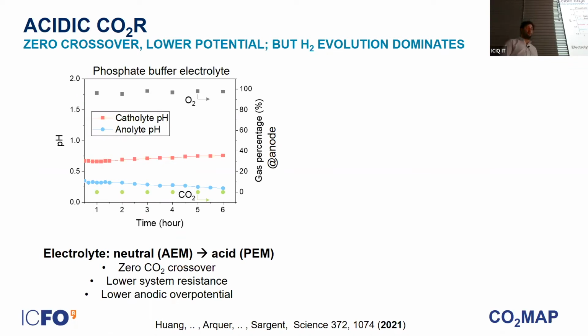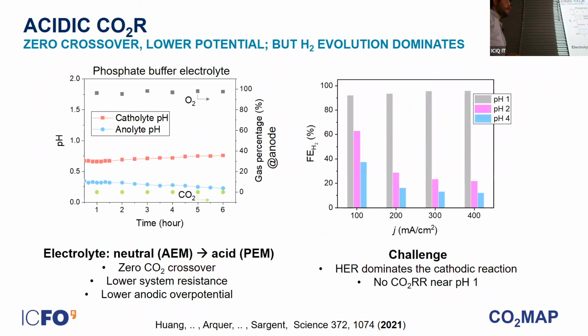We have, in principle, lower system resistance because the system is very acidic, and in principle also a lower anodic overpotential, based on the existing body of knowledge for PEM electrolyzers. But there is a problem, of course. In these acidic conditions, you have so many protons around that hydrogen evolution dominates the cathodic reaction. So you can barely do anything but hydrogen if you are operating at a very low pH. No carbon dioxide reduction occurs near pH 1.